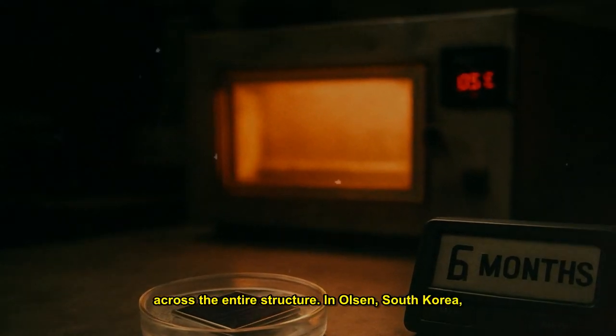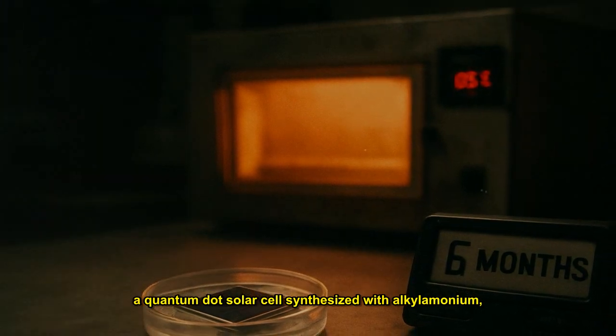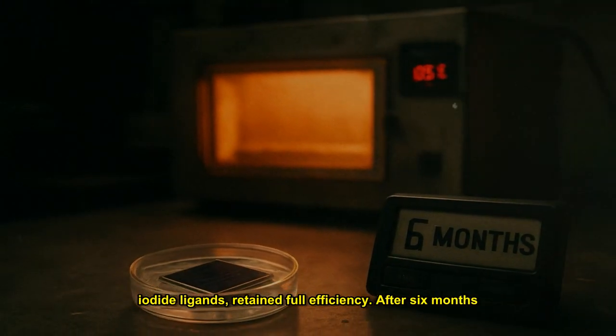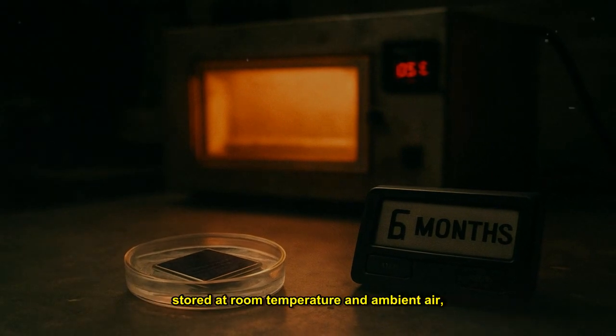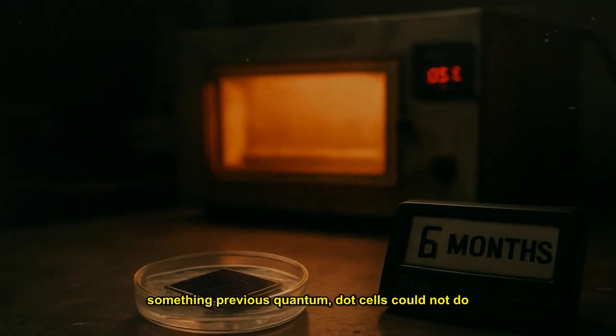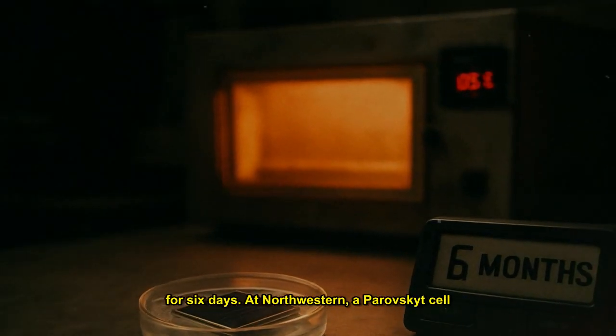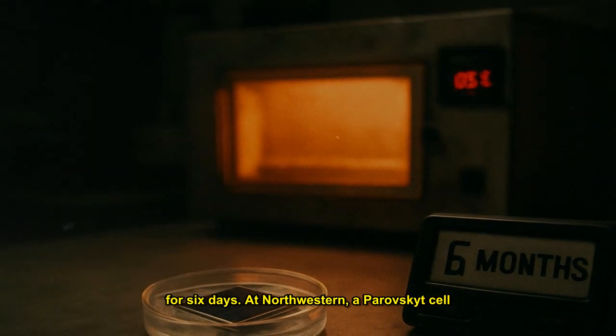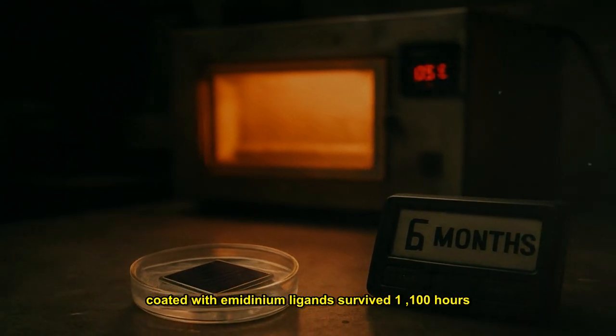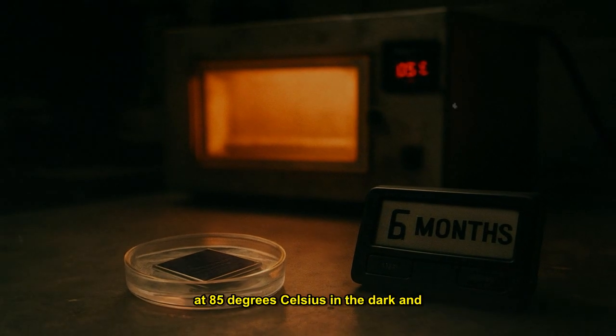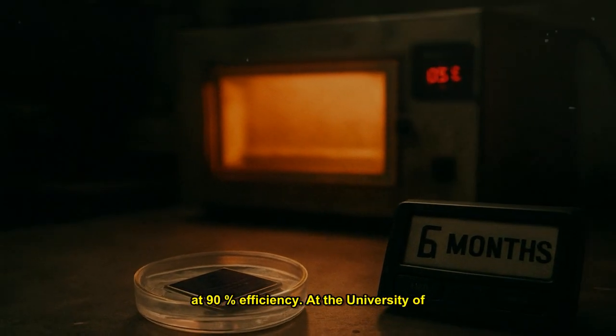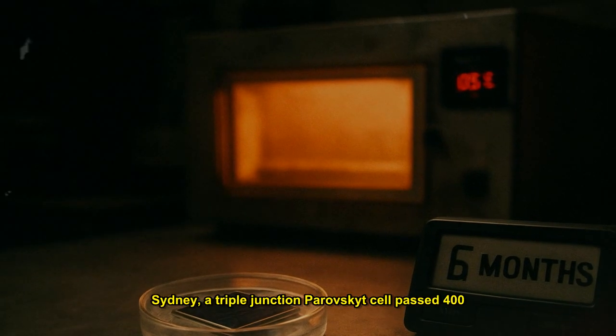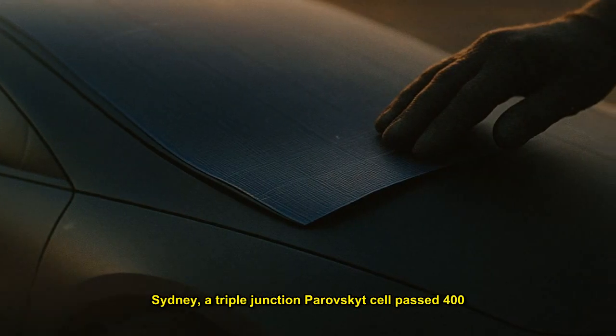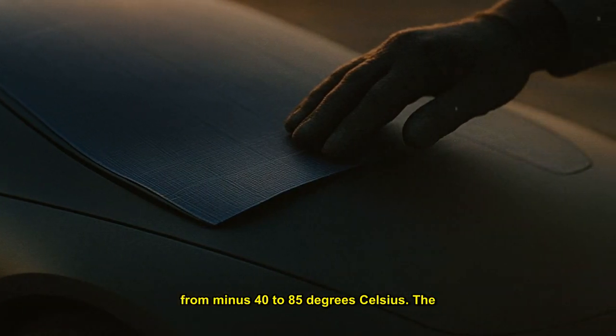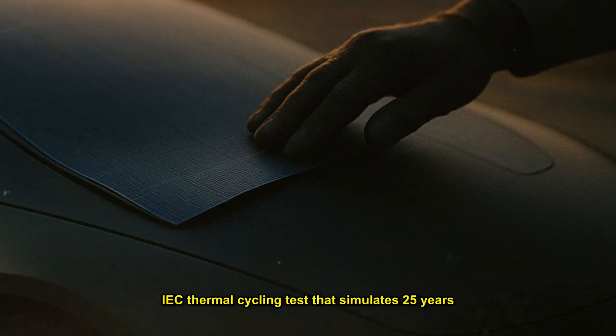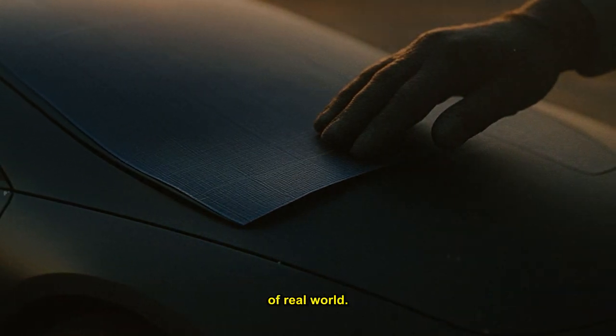In Ulsan, South Korea, a quantum dot solar cell synthesized with alkyl ammonium iodide ligands retained full efficiency after 6 months stored at room temperature in ambient air, something previous quantum dot cells could not do for 6 days. At Northwestern, a perovskite cell coated with amidinium ligands survived 1,100 hours at 85 degrees Celsius in the dark and came out at 90% efficiency. At the University of Sydney, a triple-junction perovskite cell passed 400 cycles from minus 40 to 85 degrees Celsius, the IEC thermal cycling test that simulates 25 years of real world temperature swings.